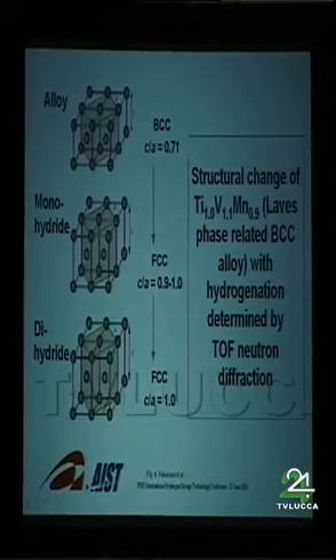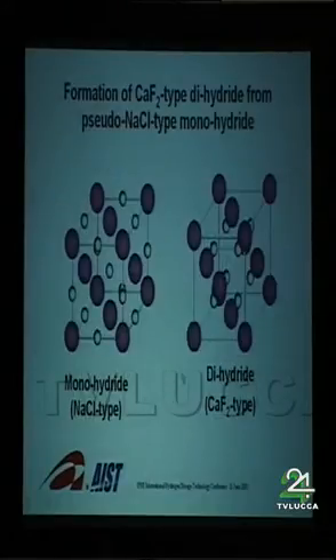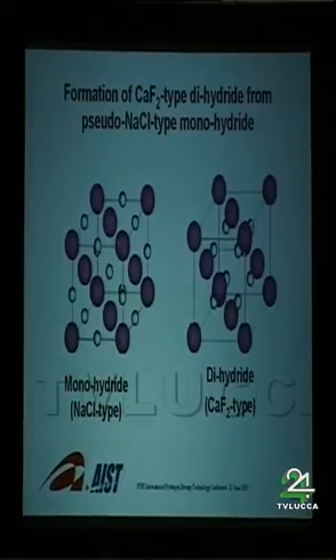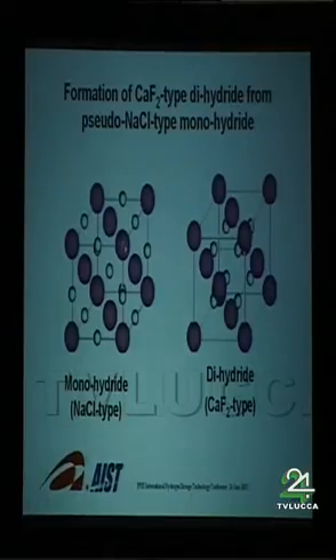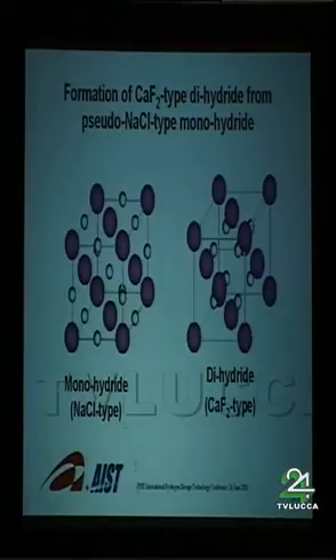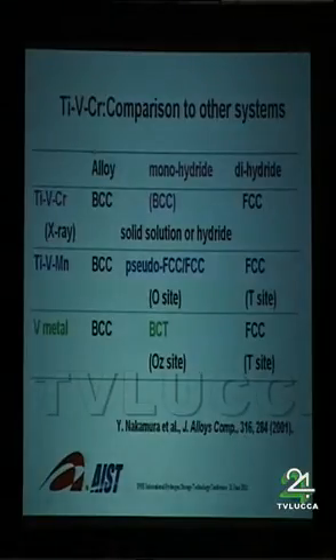But dihydride has an FCC structure. And monohydride has a sodium chloride type structure. It means the metallic sublattice was formed by an FCC phase, and the octahedral sites were occupied by hydrogen. This is a sodium chloride type structure, and this is the first time this kind of structure was found in the hydride of a transition metal. But if you put much more hydrogen into this lattice, hydrogen moves from octahedral sites to tetrahedral sites and forms a CaF2 type structure. And this is a kind of summary of titanium vanadium type BCC alloys.